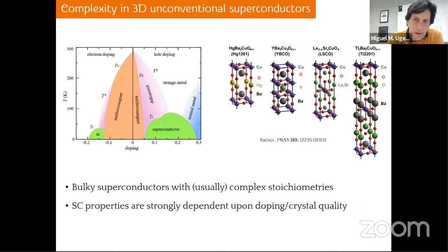The other reason is that in general, the stoichiometry of these unconventional superconductors could be quite complex. As you see here, I show you the unit cell of these cuprates, where you can see that many different atoms and planes are involved in the unit cell. And that, of course, also makes it very challenging to model these kinds of systems in order to learn about unconventional superconductivity. But it also makes it quite challenging for experimentalists who try to grow these materials or characterize them after the growth, and it usually leads to quite different results.